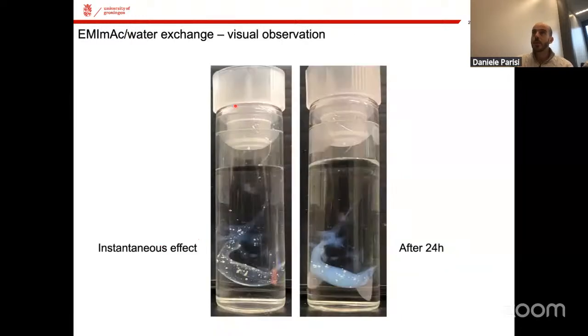So this is how, for instance, a stripe of ionic liquid looks when it's completely dipped into water. This is basically the instantaneous effect we have. And this is basically how this sort of hydrogel becomes after 24 hours. You see that it becomes very turbid, very opaque, hinting at the formation of very large clusters, or at least of the order of microns.